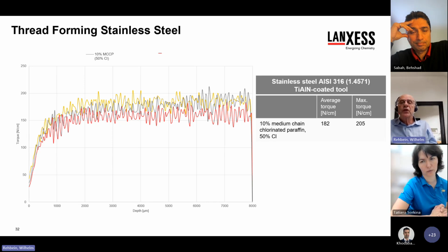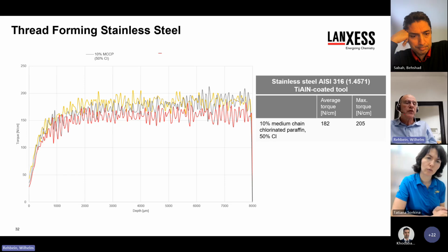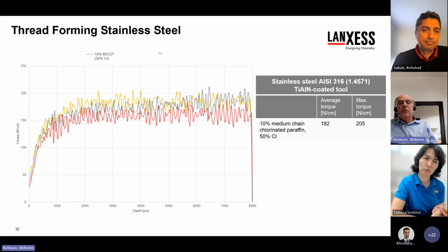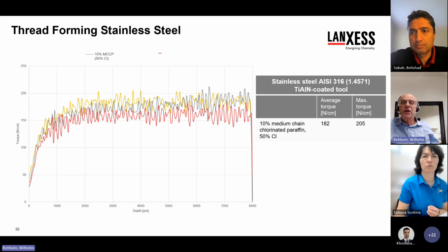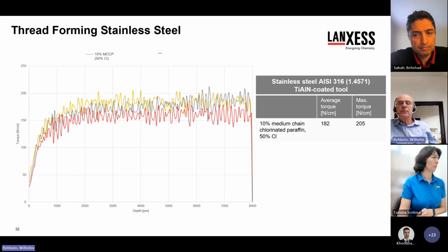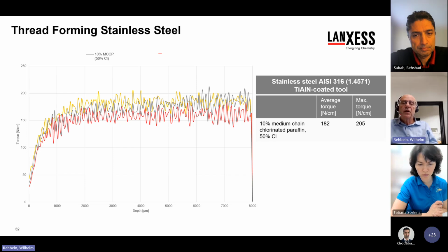And compared with this formulation, the formulation containing 10% sulfurized ester showed a slightly lower average torque, but a higher maximum torque. And this is probably caused by the lower viscosity and the lower lubricity of the sulfurized ester. But then we ran the test with 10% of the active sulfurized triglyceride, and due to the higher polarity of its molecular structure, the torque of the active sulfurized triglyceride was significantly lower and also much lower than for the chlorinated paraffin.